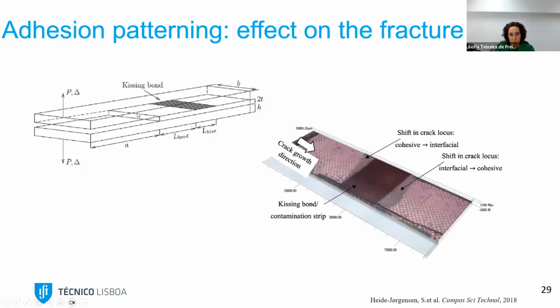So what we did was putting some contamination strips. And here you can see the fracture surface. So you see the crack growing inside the adhesive, then shifting from the adhesive to the interface. And then again, once the defect was over, we shifted from the interface back to the cohesive. So by changing this crack locus, we saw a phenomenon that was coming afterwards. And this was inspiration for future work.